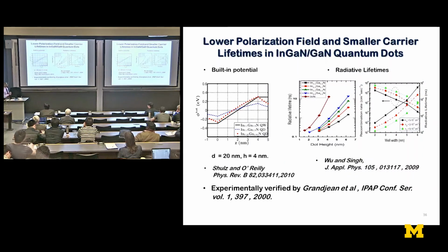And so two papers arrived. An early paper by Ian O'Reilly in Cork in Ireland, and he calculated the polarization field in quantum wells and nitride wells and dots and so on. And he showed that the polarization field is much smaller in quantum dots. And it's expected because these quantum dots grow by strain relaxation. And that's what he showed.